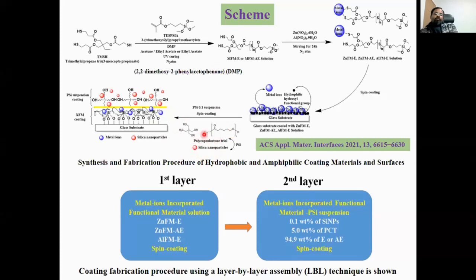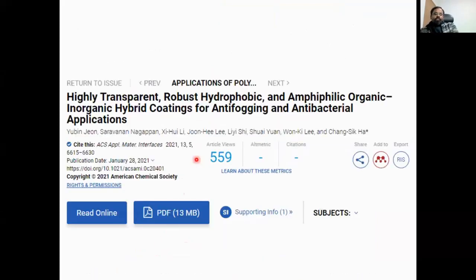We form some suspensions, and then coat this suspension on the hydrophobic coated substrate, so the layer by layer technique we used to adapt this highly hydrophobic as well as hydrophilic coated substrate, so that we can use these as preferred substrates for anti-fogging as well as antibacterial applications. So the manuscript has more details, you can find them there.